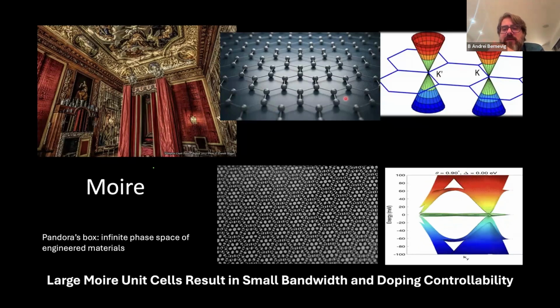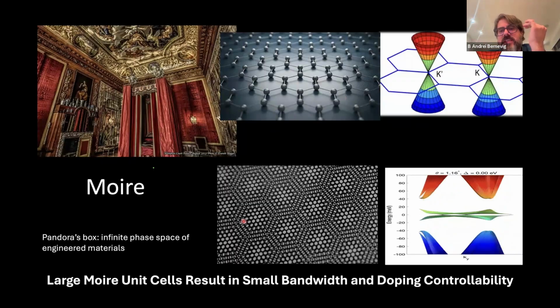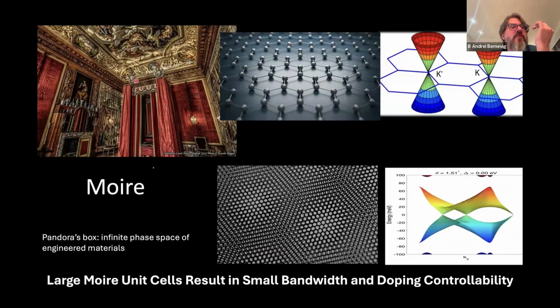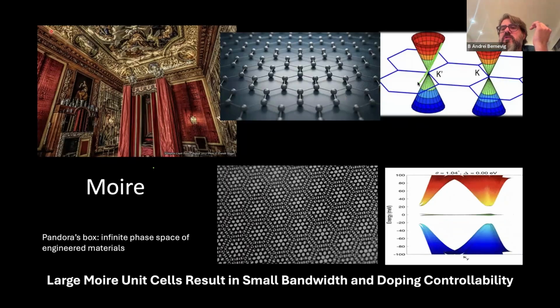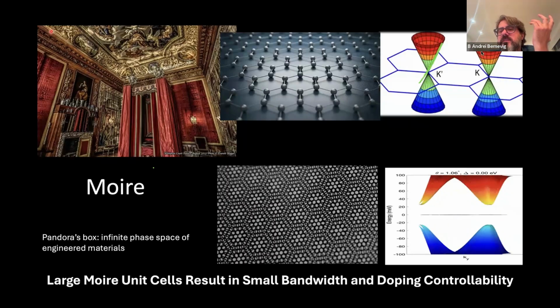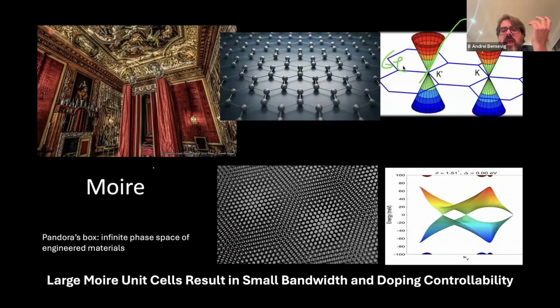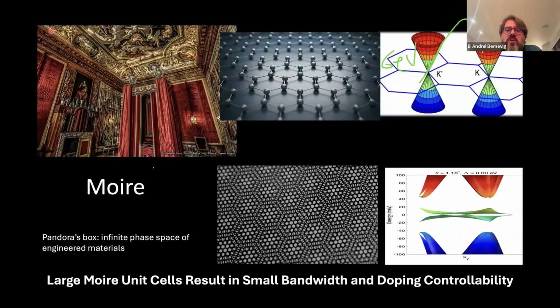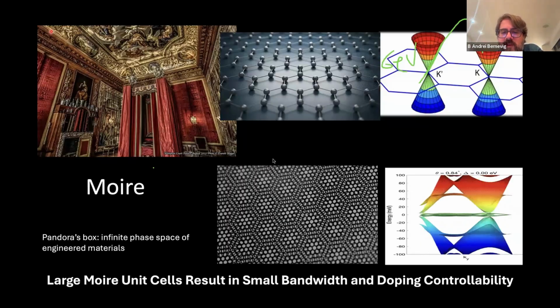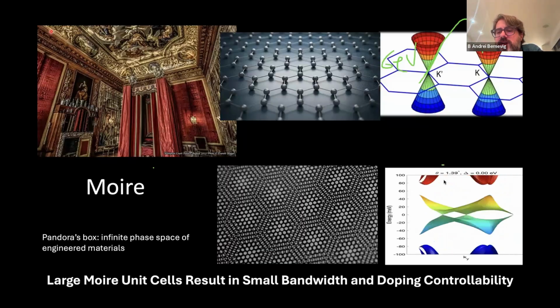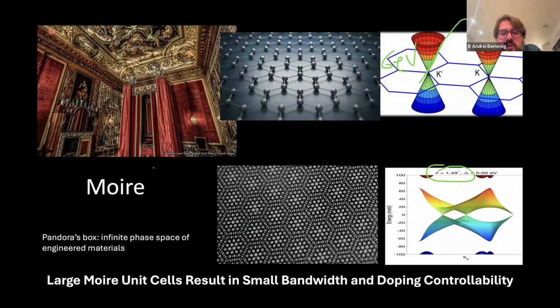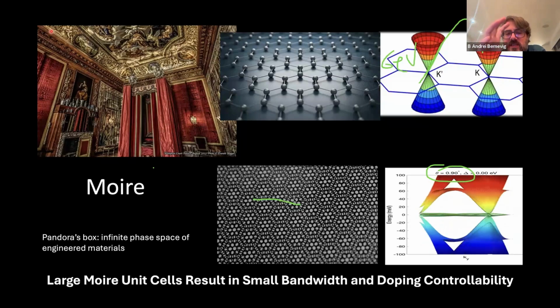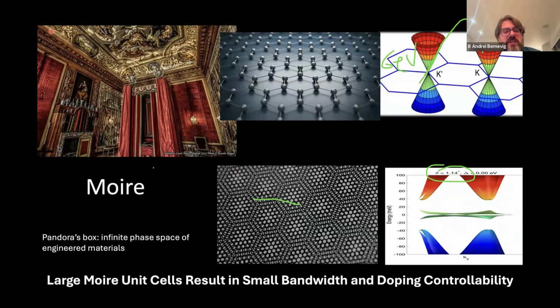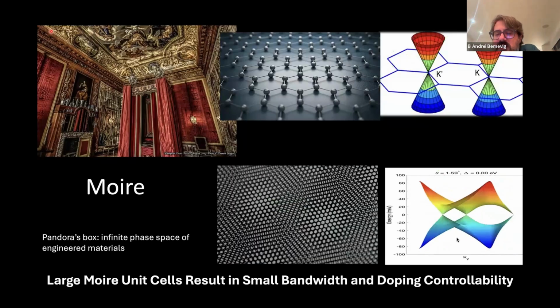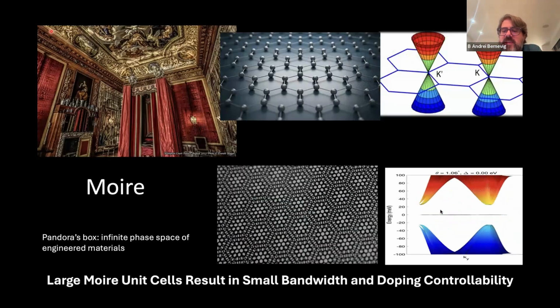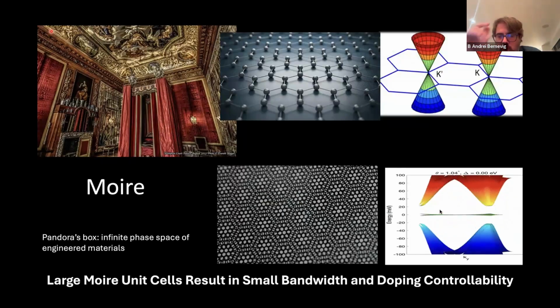The first thing that was done is graphene, which is still kind of like the grandparent of all these. And in graphene, what this does, and I'm going to go a little bit faster, is to take this huge dispersion that I showed you before, right? This is dispersion that I told you is basically 6 electron volts. And notice that as you twist 2 layers of graphene by a small angle, 1 degree, you're going to get a new periodicity, right? You can see clearly the new periodicity. So the unit cell becomes much larger. But then because the unit cell becomes much larger, the momentum space becomes much smaller.